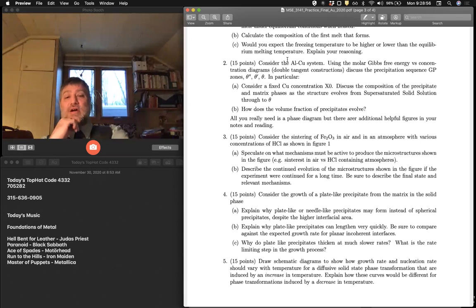So I say consider aluminum copper, right? This was a system we talked about in a little bit of detail, and specifically, we talked about the precipitation sequence of GP zones, theta double prime, theta prime, and theta, right? And we remember from the phase diagram that theta is the thermodynamically stable phase, right? GP zones and these other phases are the metastable phases, right?